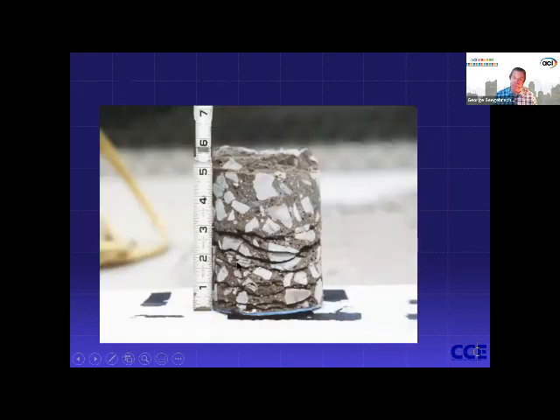Here, this is over years and years. It's an upside down core. Here's the painted surface of the pool, and this cracking extended well past 3 inches. If you're going to fix this, you'd have to take it down to sound concrete. But they actually removed this pool.